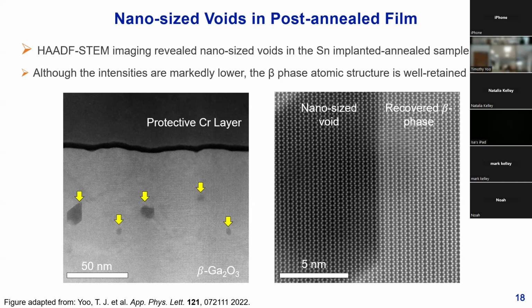So, I guess that's a good question in terms of why are we calling it a void if there's no actual vacancy? I would say that there's still actually a high concentration of vacancies here. We do have EDS data that shows that the concentration of gallium significantly decreases within this region. I don't think I have that as a slide here, unfortunately. It is within the paper that was published, but initially we were calling it a vacancy cluster. Some of the comments that came back were that vacancy clusters are usually a couple atoms, within a few unit cells, and this is obviously a much larger region. And so that's why we resorted to calling it a nanovoid. I think the terminology can definitely be a little bit more flexible, but that's just what I landed on at the end.